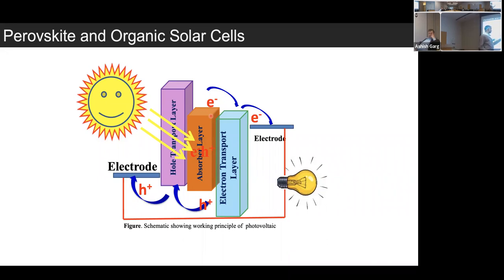The good thing about this device structure is that most of these layers can be solution processed. And perovskite and organic solar cells are basically chemistry-based compounds, so you can easily tune their band gap, change their compositions and other optoelectronic properties. Since you can make them using solution processing, either on glass or on flexible substrate, they offer many kinds of applications, especially in conformal electronics. There are issues, however. In organics, the efficiency is low: about 15–16% for single junction devices, which is high for organics, but low compared to perovskite at about 25% at the moment, and even silicon at about 26%.